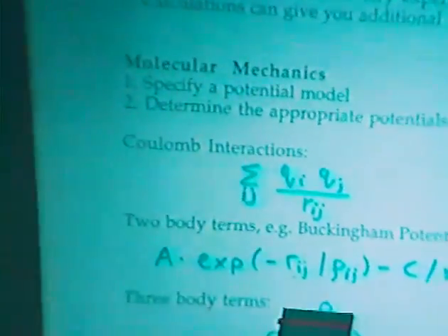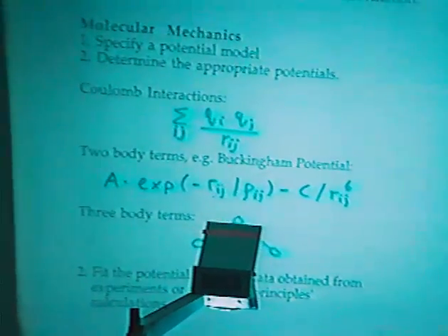Just one example of things we do is molecular mechanics, dynamics, energy minimization. We always start with specifying a potential model. What kind of potentials are involved in my specific material? It depends: is it ionic, is it polar, highly polarized, like zeolites or metal oxides, or is it just an organic molecule? Some kind of interaction you can use is just simple Coulomb interactions, long-range interaction, very important in ionic materials. And you just represent that with a term like this. And you sum that over all neighbors.